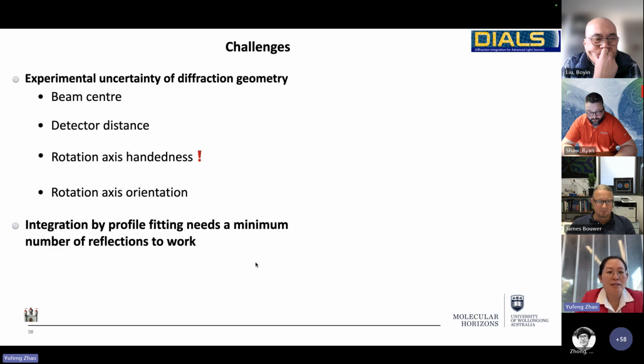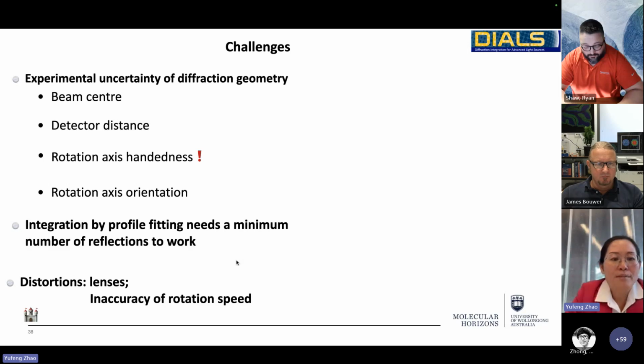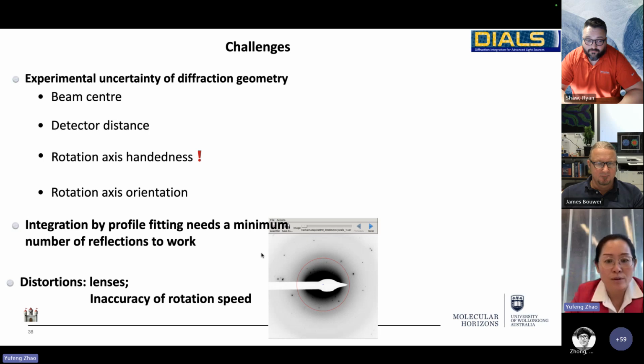Other challenges: we need enough good diffraction. Sometimes you spend a long time on the experiment and get some diffraction, and you really want some result, but you may be able to process it yet not pass the integration step, because we need enough reflections to be able to get a model. Distortion also happens a lot, like lenses not calibrated well, or rotation speed or something else. This image from my early stage experiment couldn't be processed.